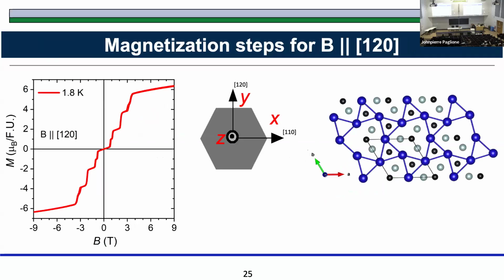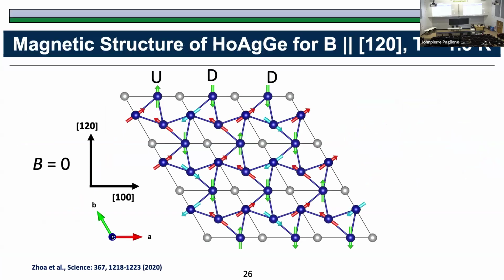Now, when we measure magnetization, it shows a lot of different steps. And these steps have to do with the twisting in the plane, because it generates huge anisotropy in the system with the holmium atom. The choice of atom also matters. Particularly with holmium, it generates huge anisotropy in the plane. And then by applying an external magnetic field, you can change that, and you get these magnetization steps. We are fortunate because this compound was studied for a different reason. They were just studying the huge anisotropy in the system, and it was even published in Science. They proposed this as a perfect spin ice system.